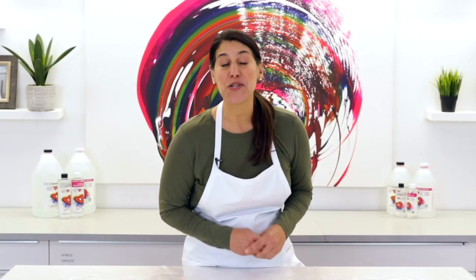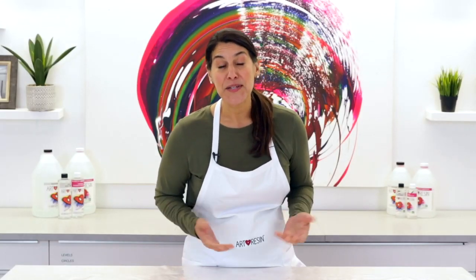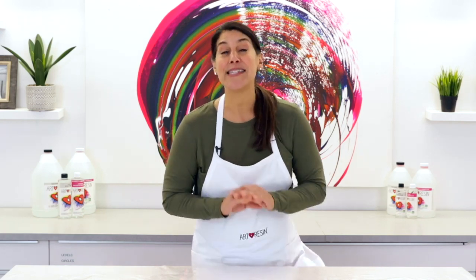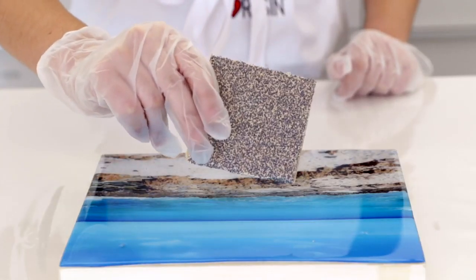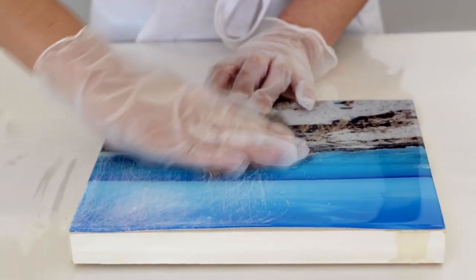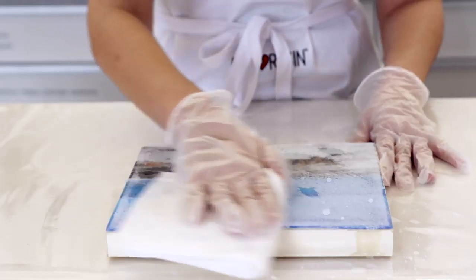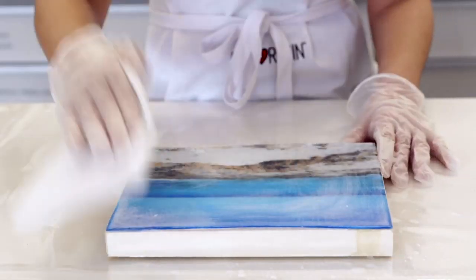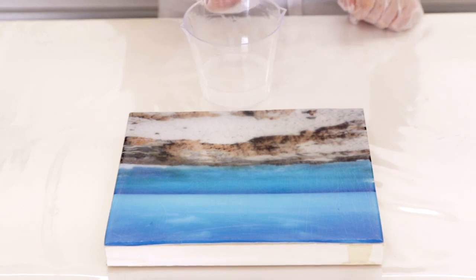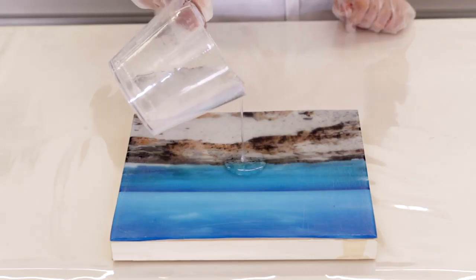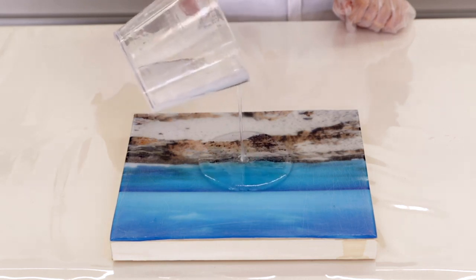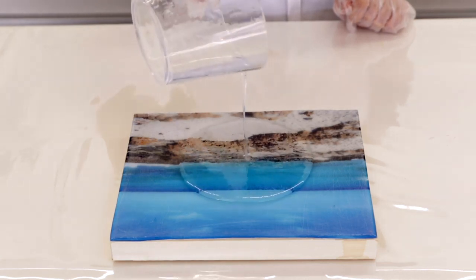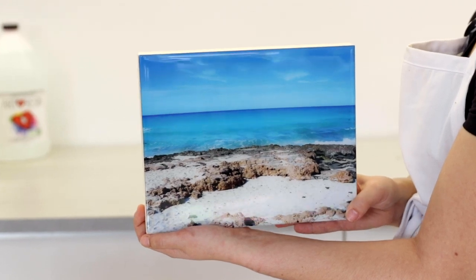So say you find some bubbles in your cured resin. What do? Well, first of all, don't worry. This is an easy fix. Grab some coarse sandpaper, like 80 grit, sand down the entire surface, including the bubbles, and be careful not to damage your artwork. Wipe away all the sanding dust with damp paper towel. It'll look like a mess at this point, but that's okay. Once your surface is totally clean of any sanding residue, pour a fresh coat of ArtResin. The scratches will disappear before your eyes, and once your piece cures, you'll never know there were ever any bubbles.